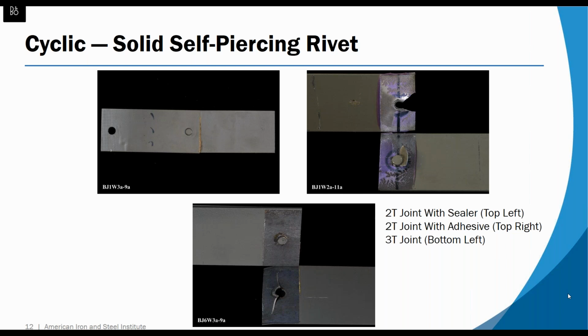However, on the upper right-hand side with the structural adhesive, we see the failure mode actually changes, and we see a failure at the rivet where the stress concentration is, instead of failing the top sheet. And in the bottom sheet, it is again somewhat different because we are failing by pulling a nugget out of the bottom sheet rather than cracking through the top sheet.